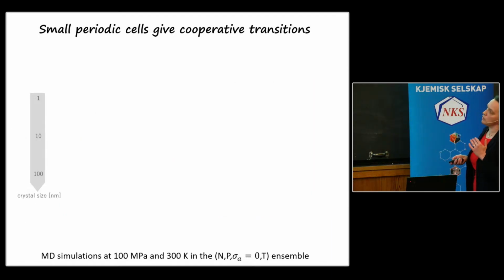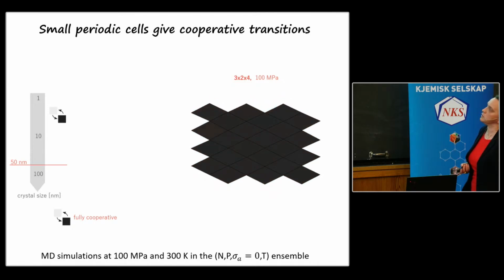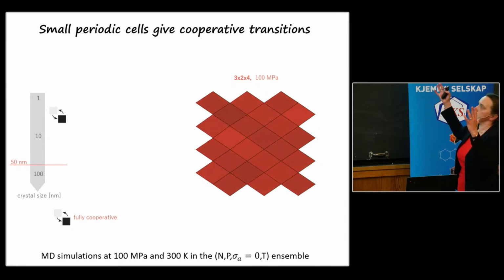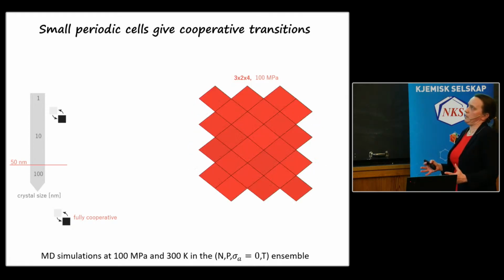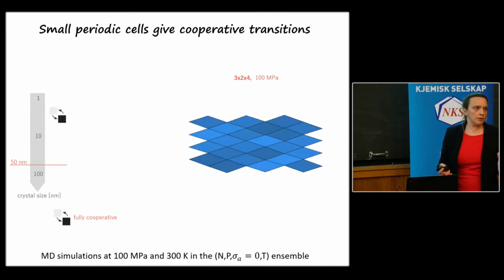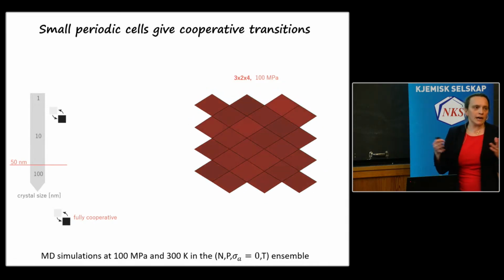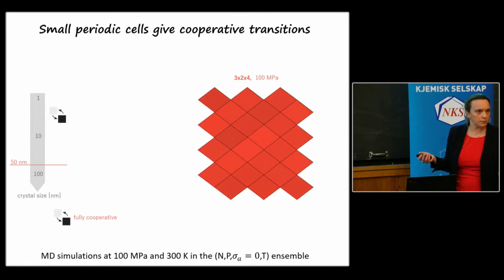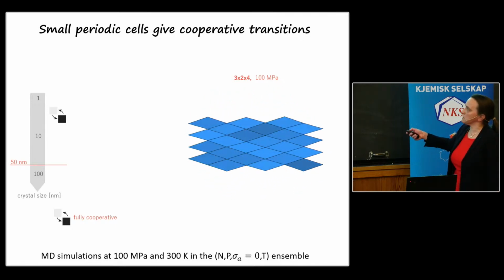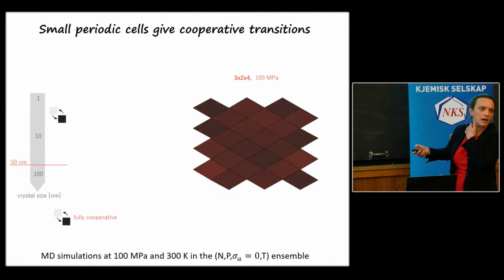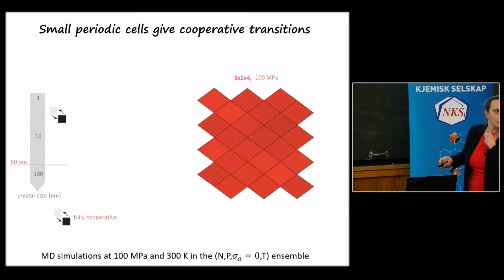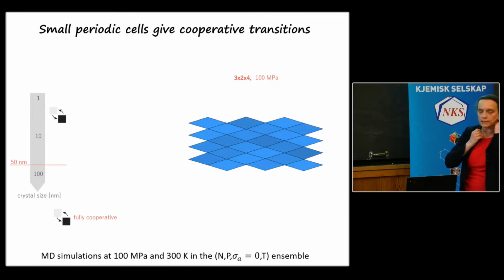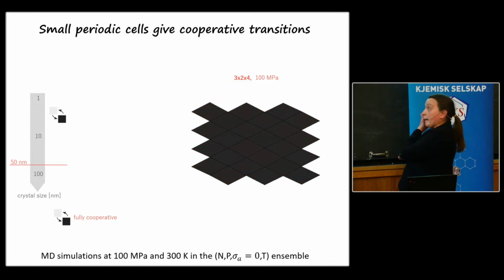If we do simulations on small systems, then we can see that everything collapses cooperatively. It's normal that we see that, because our system is so small that you cannot allow disorder in this system. Here, the system you simulate is so small that you have no disorder. You do not allow disorder. This is typically the result of the simulations.